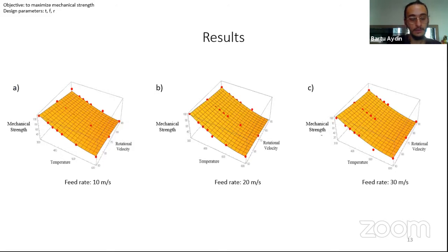Here, there are some 3D plot representations of the comparison between experimental and recommended model results on mechanical strength in terms of temperature and rotational velocity. Feed rates are taken here as 10, 20, and 30 meters per second, respectively. You can see from the graphs, red dots represent the experimental data, and the yellow area represents the proposed regression model. And we can interpret from these 3D plot representations that the proposed model fits well with experimental results because the yellow area overlaps with red dots.